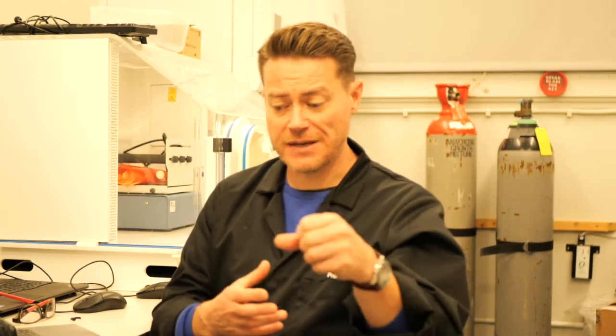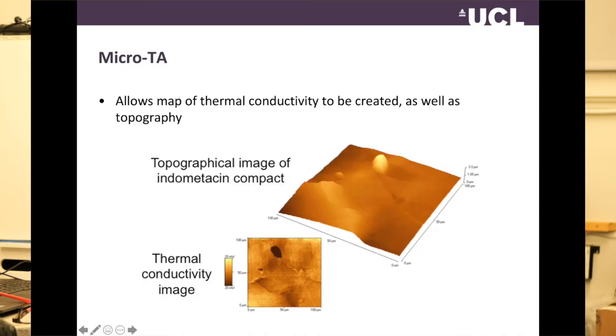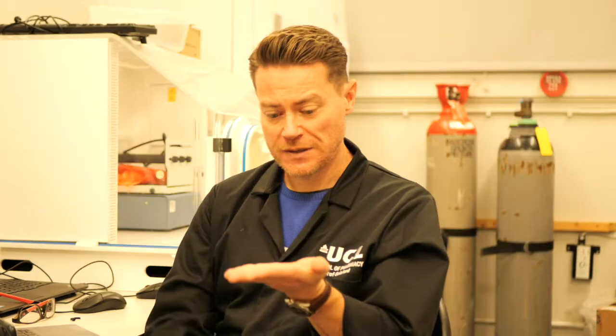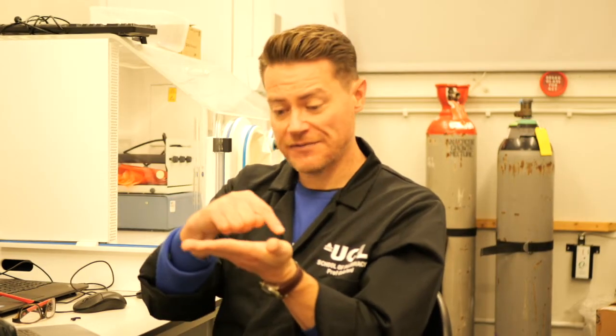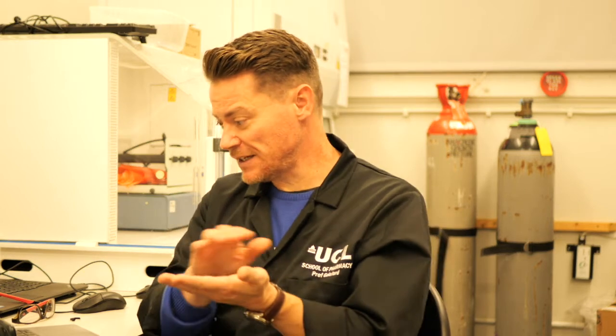So this image is indomethacin in a tablet, and so the way that works is indomethacin particles mixed with excipients and then compressed into a tablet. And the question is, where is the indomethacin in the tablet? Is it discrete particles? Did it blend well, or whatever? So the big image is simply showing you the topographical data as recorded by the AFM for that tablet, and you can see it's relatively smooth, and there's just one bit that looks a bit high at the back, which is in yellow, so it looks like something is sticking up.